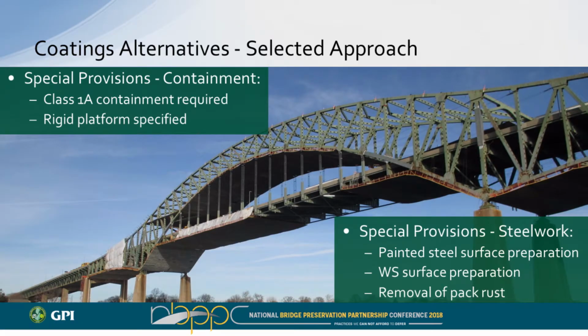But okay, for our painted steelwork special provisions, painted steel surface prep, SSPC SP10, NACE number 2, the near white blasting, a near white surface, was required throughout. Weathering steel surface prep. Now, weathering steel is a different animal because the surface profile is so drastically different than a regular steel member, where you've got very high peaks and low lows. Now, this is microscopic level, but very high peaks and low valleys.